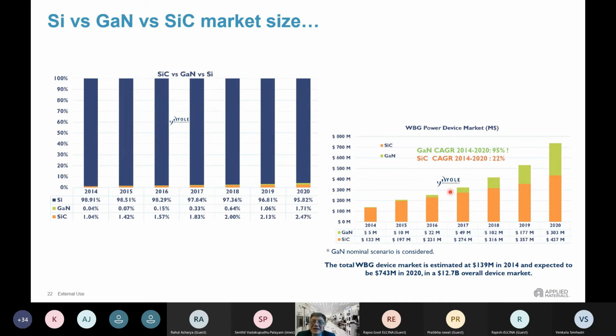And the markets are interestingly growing at a phenomenal pace. Take a look at the gallium nitride growth rate, which was projected for 14 to 20 at 95%, and silicon carbide, which was at 22%. Now, these are very, very high growth rates. 22% growth rate is not small either. But of course, gallium nitride has been growing very rapidly because it is at the low end, and low end is where the consumer markets are, and they are now taking traction of this particular device technology.